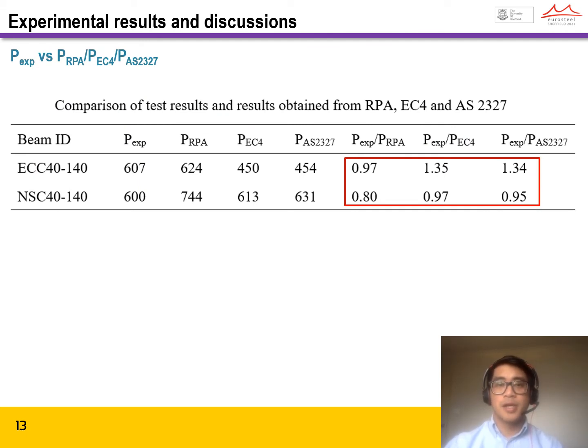The strength of the tested beams was compared with the results obtained by rigid plastic analysis, the European EC4 standard, and the AS 2327 standard. It is clearly seen here that for the ECC beam, the rigid plastic analysis result is pretty much similar to the test result, which demonstrated that the plastic development was rich in this beam. While for the NSC beam, even though it failed in longitudinal shear, the NSC almost reached its ultimate strain. However, the result of the rigid plastic analysis over-predicted the experimental results.